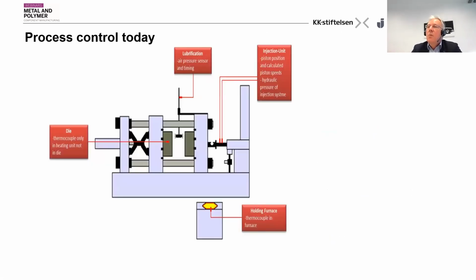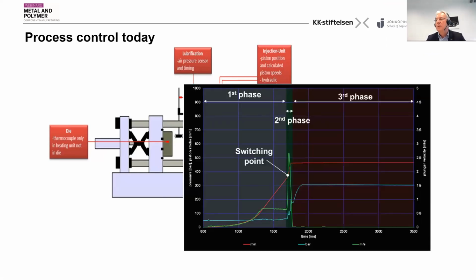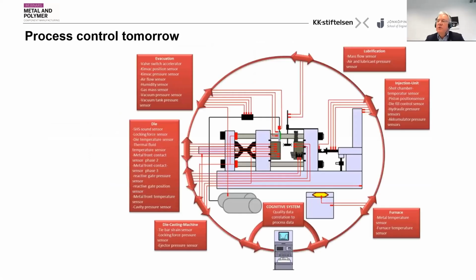What do we control today? Basically not a lot. We have a temperature in the holding furnace. We have the injection unit where we at least have a shot profile. Lubrication, only some people do it, and die thermocouples, I don't think a lot of die casters use them. So what we get is this shot profile, first stage, second stage, third stage, pressures and velocities of the plunger, and then we can calculate the velocity of the melt and stuff like this. And we can get a lot of information from this. But the dream of a high pressure die caster is to understand the process. And this is what I'm going to talk about in the next 20 minutes. What should we use? Control much more data from the evacuation, from the die cast machine, from the lubrication and everything.